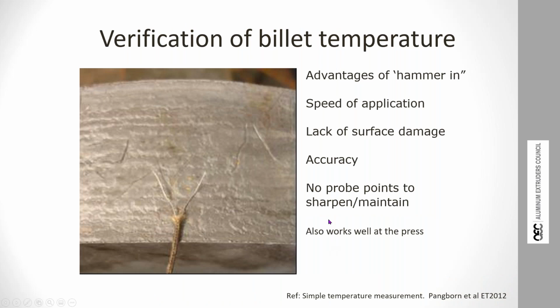And you also want to be verifying what you're seeing. This is a technique Johnny Pangborn presented at ET 2012. It's just two open thermocouple wires, and you can see where he's done it several times in the surface here. He puts them on the billet and he hits them with a hammer. They give a very accurate reading. There's no mass in these, and they're in good contact totally with the surface because they're being hammered in, and it's very quick. And I can recommend you to have a look at Johnny Pangborn et al.'s paper from ET 2012.